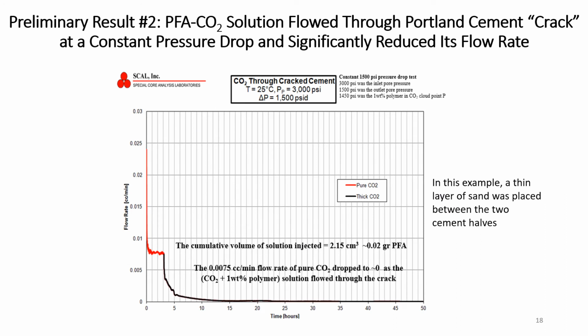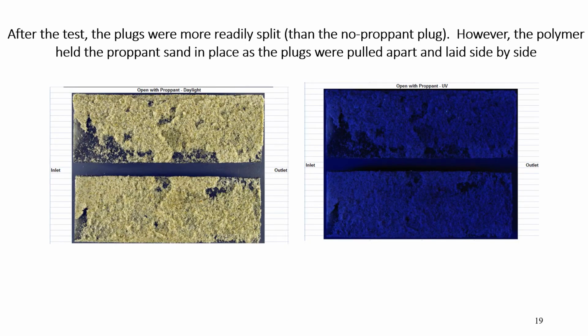An additional test was performed where we added a sand prop into the cement crack and flowed the PFA solution at a constant pressure drop. Over time, the flow rate reduced to 0. After the test, the polymer was holding the proppant in place, showing deposition had occurred again.